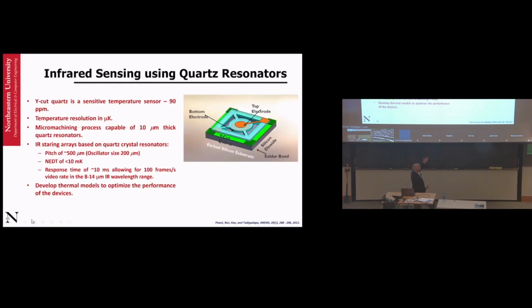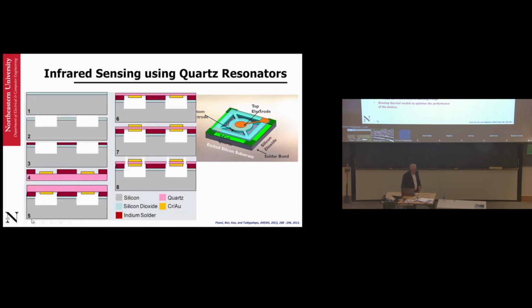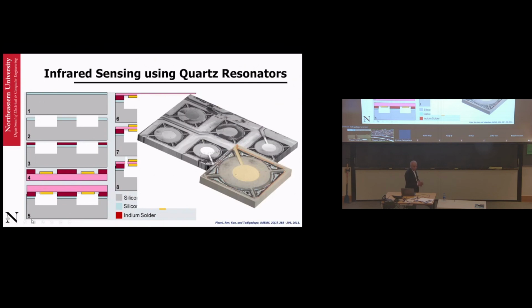You can also make these into infrared detectors for the same reason. And so this is complex integration. You can thin the quartz down, you can make them into resonators, and you put it on a silicon chip that has been pre-etched. I'm not showing you all the details, as I say here, but there's a fabrication process, very complex, but nonetheless, you can make them into arrays of these infrared sensors. The cartoons always look better than the real images, but nonetheless, they work. And that's the important point.